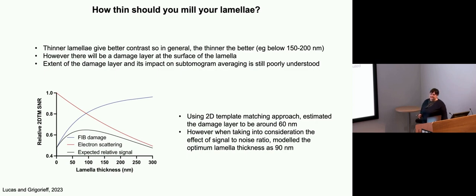However, they then also modeled in the effect of the signal to noise ratio and came up with this optimum thickness of 90 nanometers. I think there's just not enough, I think we need some more high resolution structures coming out of these lamellae to hopefully get a better understanding of whether there is a point where you get too thin and you should stop milling.